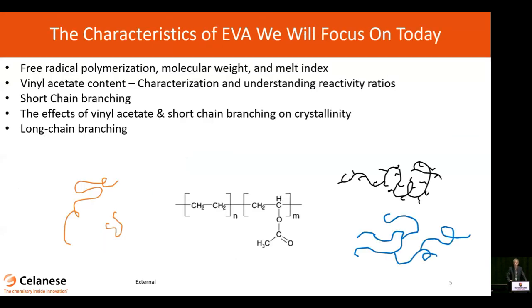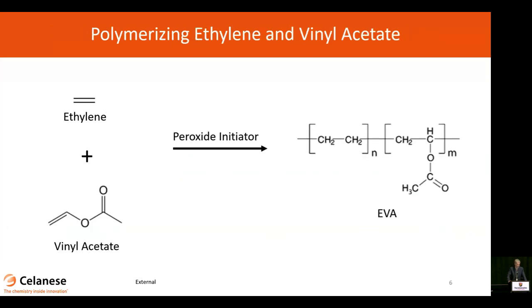So that brings us to what we're going to talk about today. We're going to talk today about some of the characteristics of ethylene vinyl acetate copolymers, which is shown here. The structure is a copolymer of ethylene and vinyl acetate. So we'll first talk a little bit about the polymerization, molecular weight effects, and how that might be indexed and characterized. We'll talk a bit about vinyl acetate content. That's a very, very critical parameter for describing the drug release characteristics of the material. And then we'll spend maybe the last few minutes of the talk diving into some of the more complex aspects of this polymer, which is around the branching effects that occur in the chemistry.